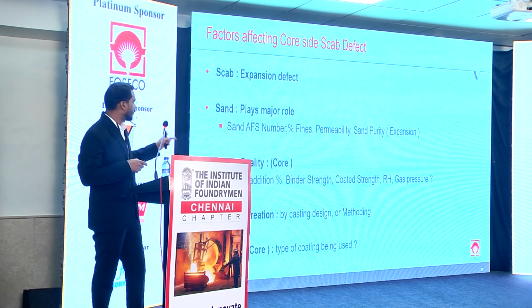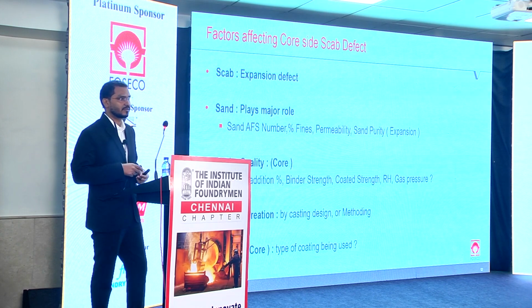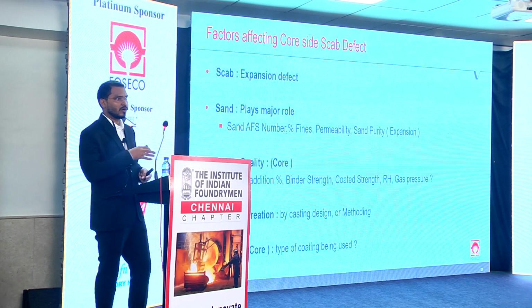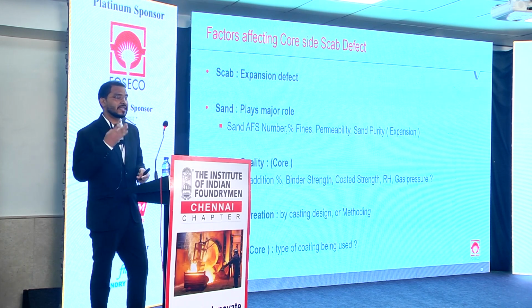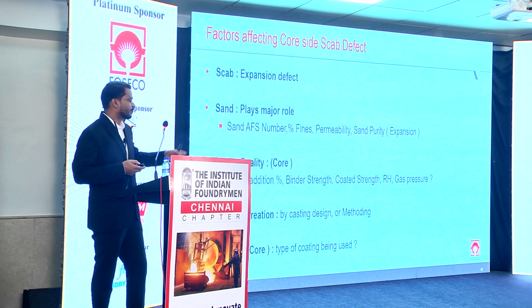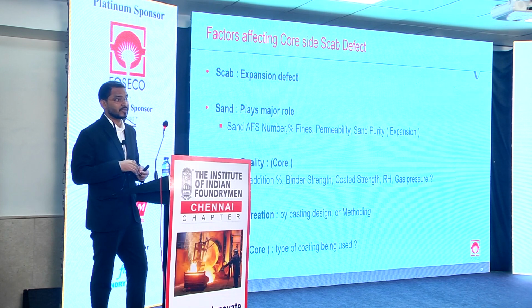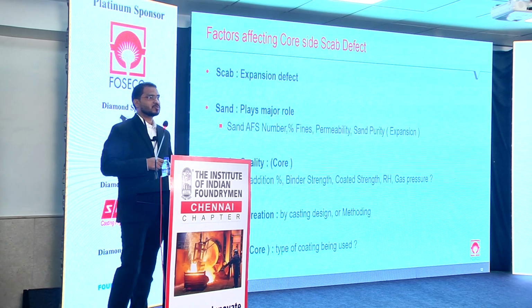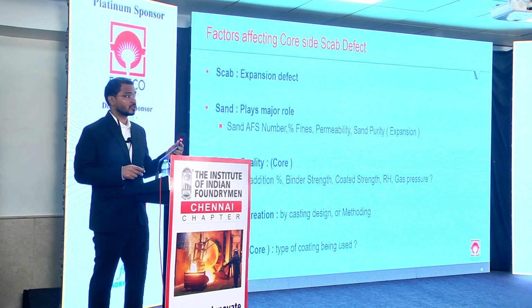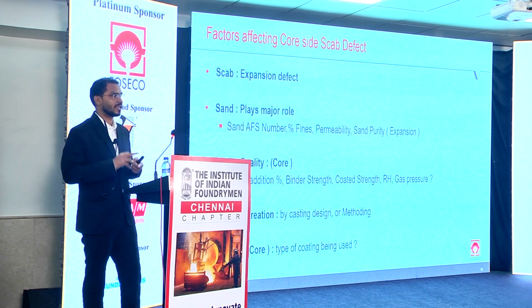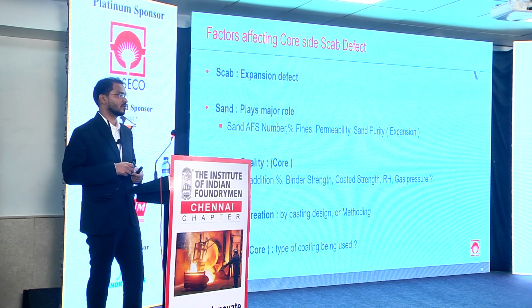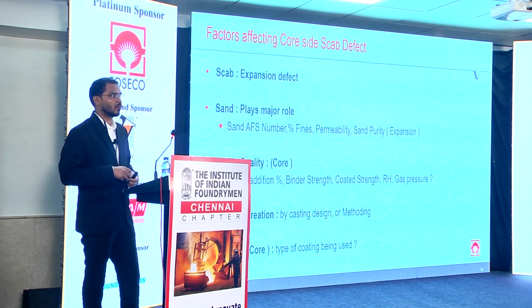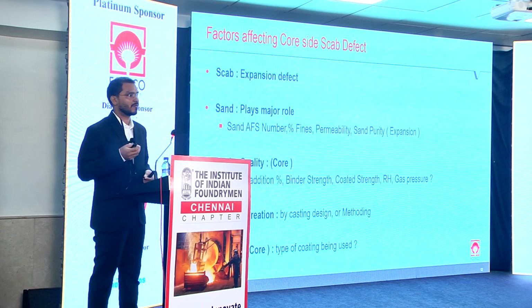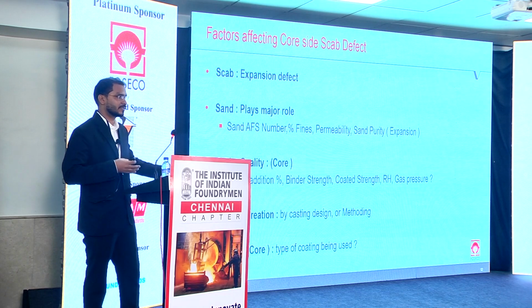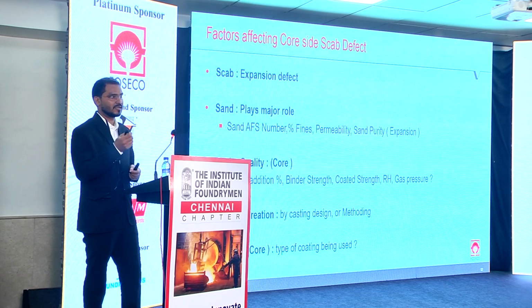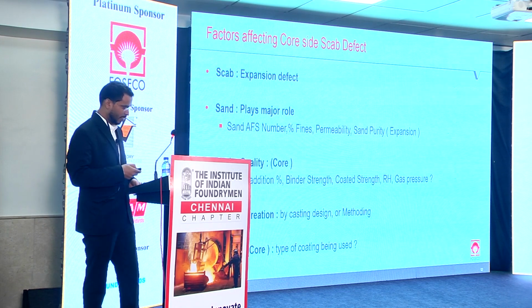So sand plays a major role, binder also plays a major role, and then coated core strength. After water-based coating on the core, there will be a drop of strength. So in that case also scab can happen. Relative humidity and temperature also play a major role. Many times we have seen that these kinds of defects can be eliminated through methoding. So hotspot design and runner and riser design also play a major role. And then lastly coating. In a foundry, the contribution of coating is hardly 1.5 to 2% of all other raw materials. So consumption wise it is very small, but its significance is very high. That is what we have realized.